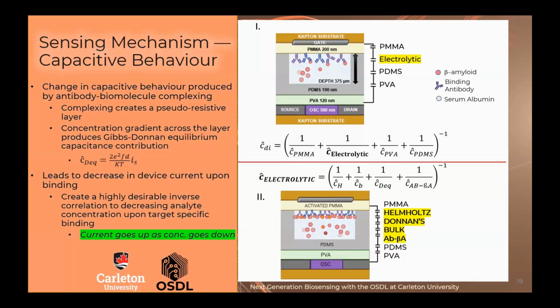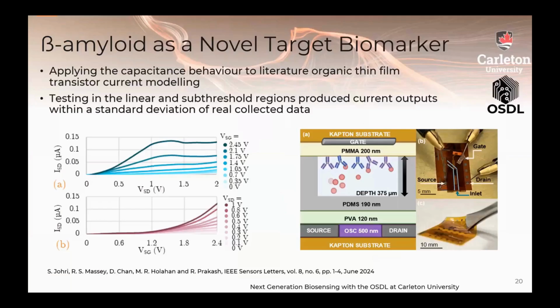For us, it's the star of the show because it allows us to minimize all the other contributions that's coming from the bulk. So the ionic effects from the bulk doesn't change the sensitive region a lot because all we are looking at is the Debye interaction. Also allows the Donnan interaction. And it also allows us to some extent overcome the Debye limit that a lot of these biosensors struggle with. Because as soon as you bind large molecules at an interface and you go out of that double layer, Helmholtz Debye double layer, your sensitivity drops.